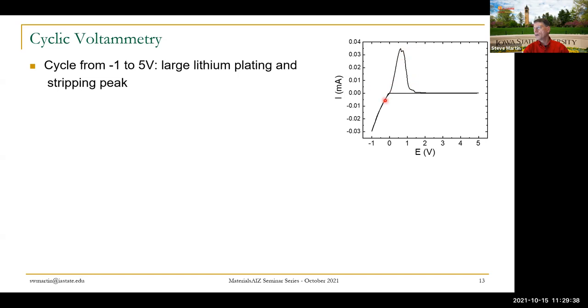And you can see here at 0 volts, this is a milliamp scale. You can see we're just plating and stripping, plating at positive current, stripping at negative. We're just plating and stripping lithium off of the lithium side of the cell. On the other side of the cell, we just go positive and nothing happens. Remember, this scale is milliamp. That would be the currents operating in the battery. But for long-term storage and long-term operation, we have to go to a finer scale to see if there isn't anything happening. So far, it looks like we're stable well out to 5 volts, but let's look a little more carefully.